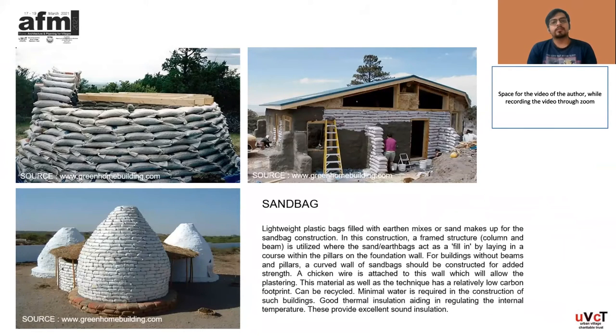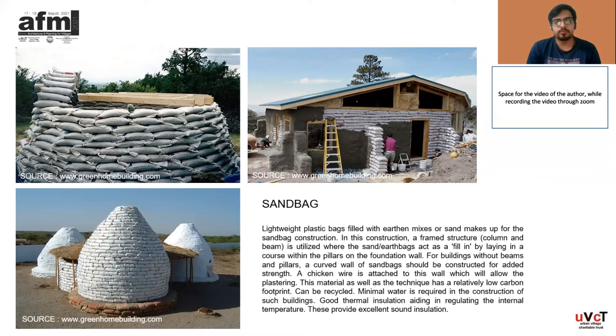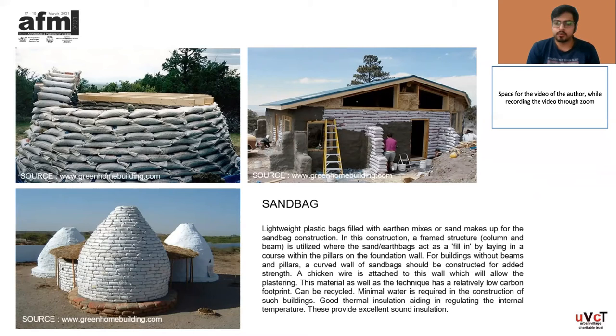Sandbag construction uses lightweight plastic bags filled with earthen mixes or sand. In this frame structure construction, columns and beams are utilized where sandbag earths act as fill-in by laying in a course within the pillars on the foundation wall. For buildings without beams and pillars, a curved wall of sandbags should be constructed for added strength. A chicken wire is then attached to the wall to allow plastering. This material and technique has a relatively low carbon footprint and can be recycled and reused. Minimal water is required, and thermal insulation aids in regulating the internal temperature.